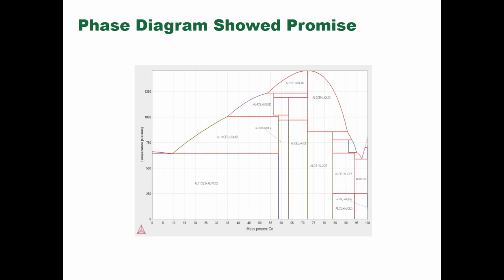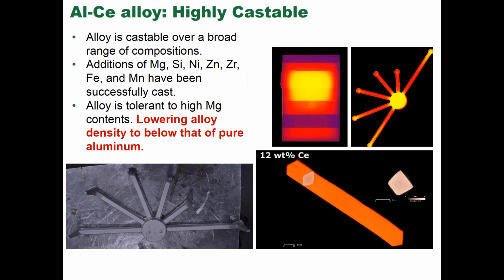I guess my reputation preceded me a little bit because the program sponsors didn't want to have a difficult to cast alloy. And so the way we started this is we started this with really a pilot program to help understand the castability of the aluminum-cerium alloy system. And it turns out it's really pretty good. The alloy is castable over a broad range of compositions. Not only do we add cerium, which gives us high temperature strength, but we add other alloying elements to improve the room temperature strength as well, and they also improve the high temperature strength when added properly.